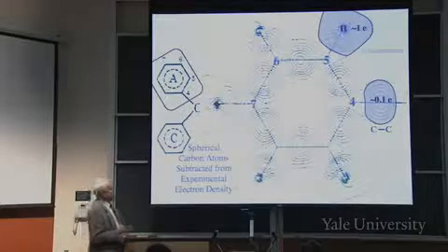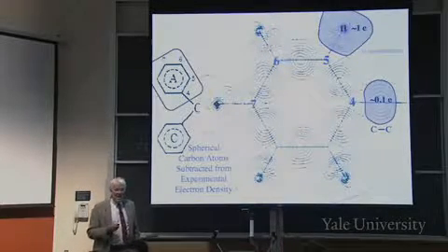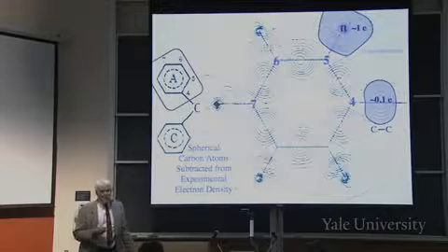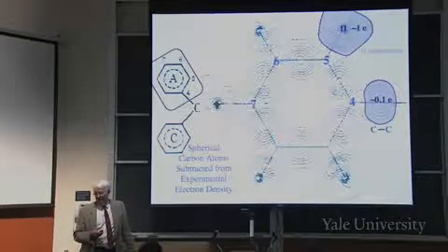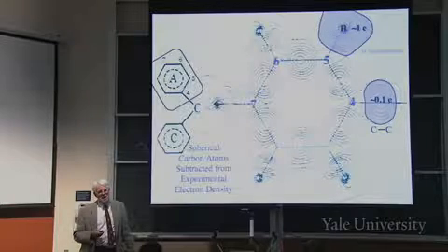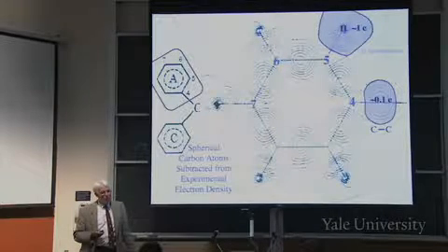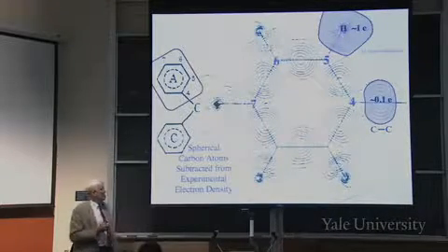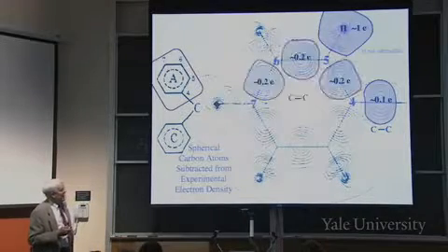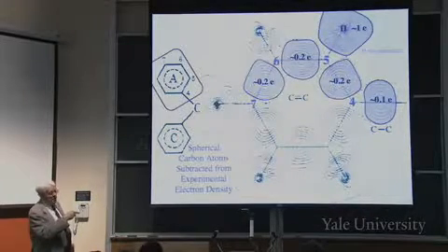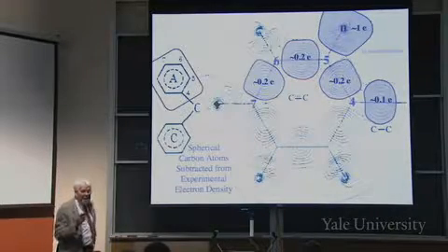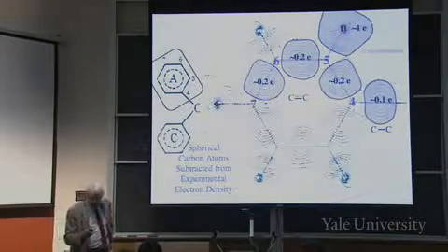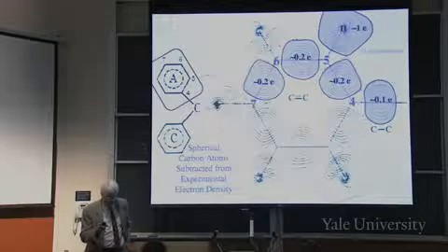But now, the total amount of deformation density in this region, where there's a single carbon-carbon bond, is only 1/10 of an electron. What would Lewis have said? 2 electrons. It's 1/10 of an electron. Okay, now let's slice that. And within the carbon-carbon bonds of the ring, the aromatic ones, it's bigger. Why bigger? Because it's partially double bond in the resonance structures, right?